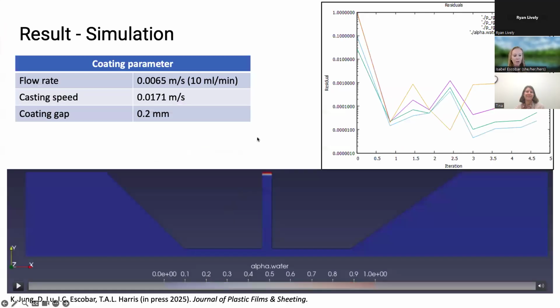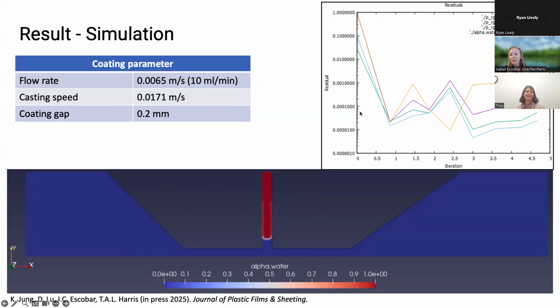And I'll show a couple of the videos, though I might move around a little bit, but in this one, this is again the side view. This is the slot die coater. This is the dope solution coming through the slot die. We can set a flow rate, we can set a casting speed, and we keep the coating gap at 0.2 millimeters here, and we look at the residual.